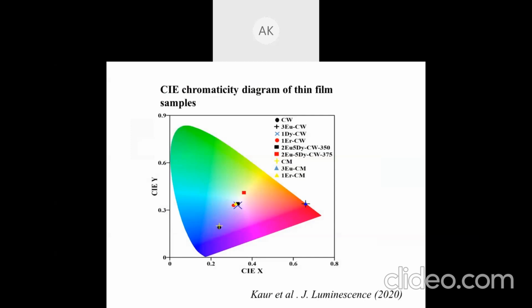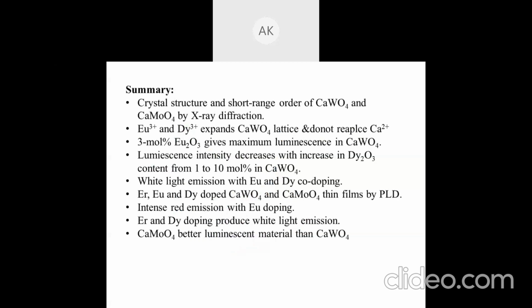And thin films also emit, again, in a similar fashion. The europium materials are red light emitting materials. And if you co-dope your samples with europium and dysprosium, then you get white light emitting materials. Their color coordinates are at the center, about 0.33 and 0.33. So I summarize: the crystal structure and short range order of calcium tungstate and calcium molybdate in the bulk form, and in the thin film form, is characterized by X-ray diffraction.